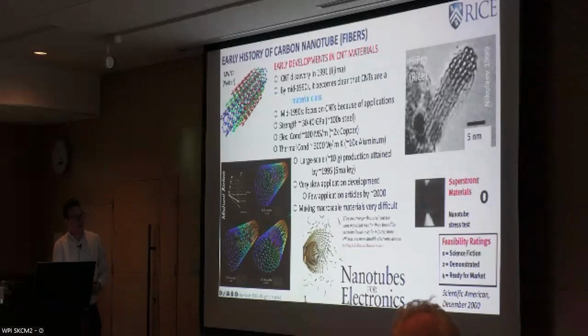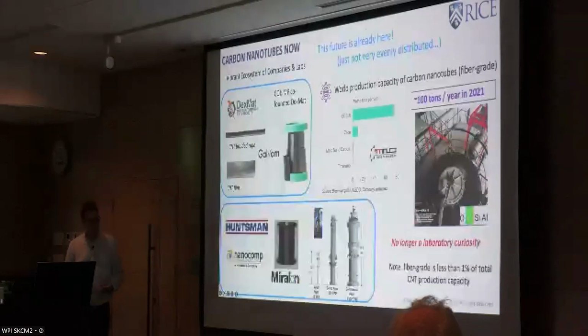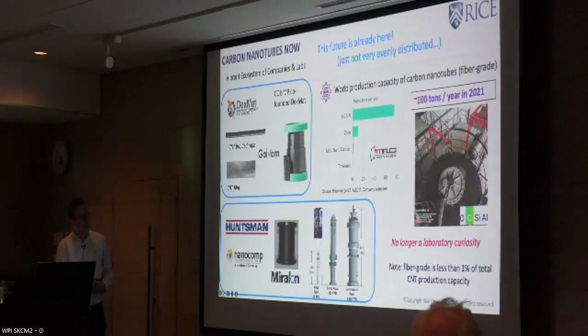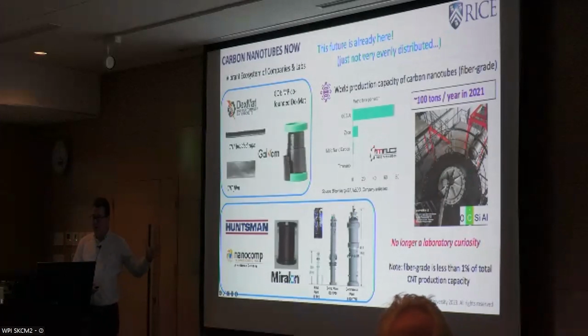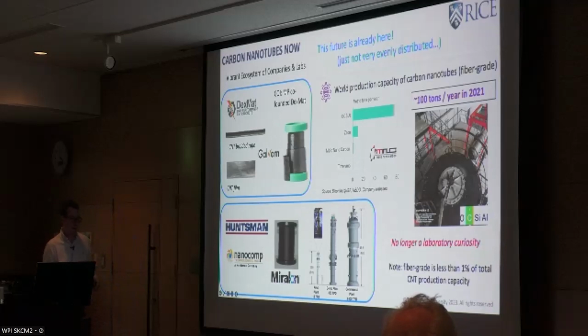And because it was very difficult to get these properties on the macro scale, and it was difficult even making macro scale material, there was a slump, and most people moved on and did something else. Now, the field has changed a lot. It's actually possible to make macro scale materials, so fibers, tapes, etc., that are only comprised of carbon nanotubes. And production has gone from lab scale to small industrial scale. I was talking about needing to make a difference at 10 million tons a year, but these are now materials that are made at between 1 and 100 tons a year, which is halfway there, because it's on a logarithmic scale. To go from a gram to a ton is about as hard as a ton to a megaton.